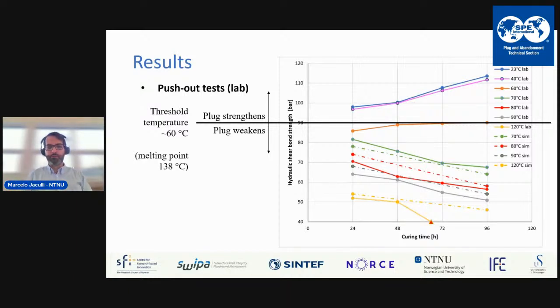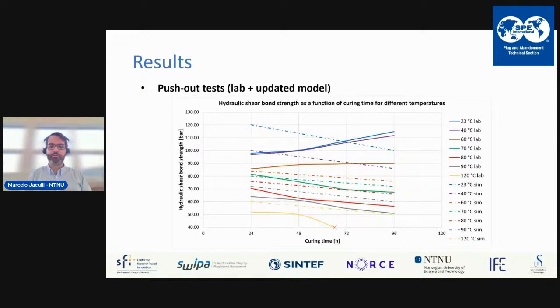But if you want to go deeper downhole, you need to make sure the maximum operating temperature for this alloy isn't surpassed by the bottom hole temperature. You can see an increasing trend for temperatures lower than 60 degrees over time, meaning as the alloy progresses over time it retains its capability of resisting applied pressure. But for temperatures higher than the threshold, as you get closer to the melting point, the performance degrades over time, and that's not what you want.